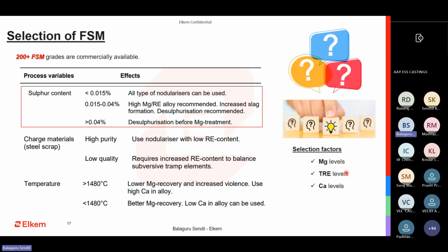So your selection of rare earth is very correlatable to the steel scrap that you are using. And the last is the calcium. Calcium is very important. It is very correlatable to your tapping temperature. If your temperature is very high, you need to have high calcium in your FSM. Calcium basically calms the reaction. When the reaction is calm, as I told earlier, you have better magnesium in the form of useful magnesium, rather than being wasted.